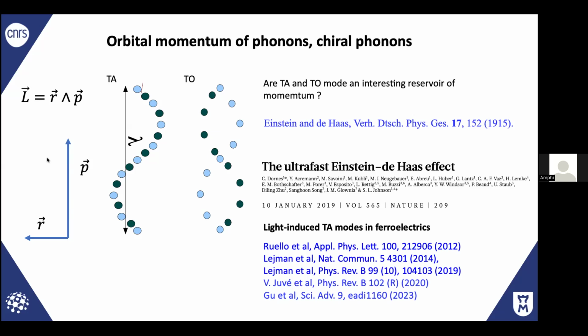People know how to do that, even in general processes. Many people just discuss chiral phonon. What are chiral phonons? You cannot generate new phonons in the solid. So a chiral phonon is just a combination of two transverse acoustic waves. That's all. But what is much more complicated is that they have to control the phase of these two transverse acoustic waves to induce what you mean by torsion. Torsion would be just a strain with a circular component, let's say orbital momentum.